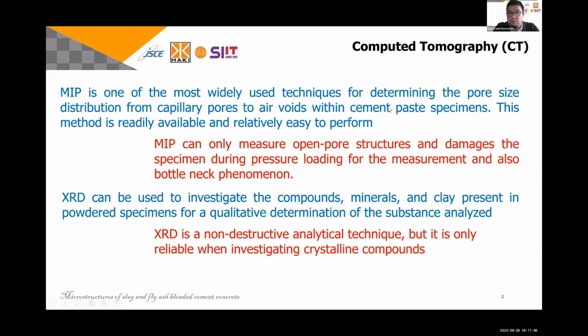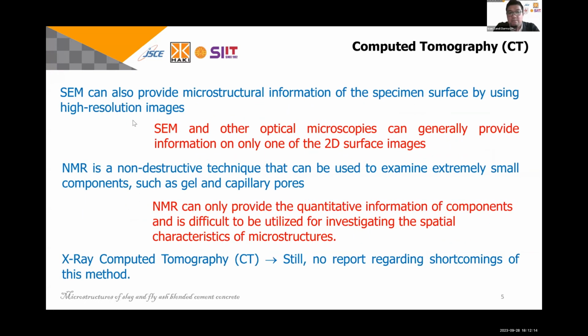And for MIP, it is one of the most widely used techniques for determining the pore size. But the drawback, as we know, is the bottleneck effect and also the damage on the specimen during the pressure loading. For XRD, the drawback is that XRD is a non-destructive analytic technique, but it's only reliable when you are investigating crystalline compounds. For SEM, we know it is only 2 dimensional.